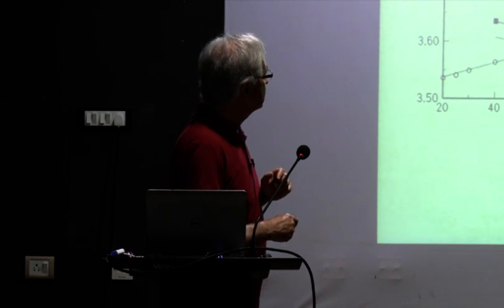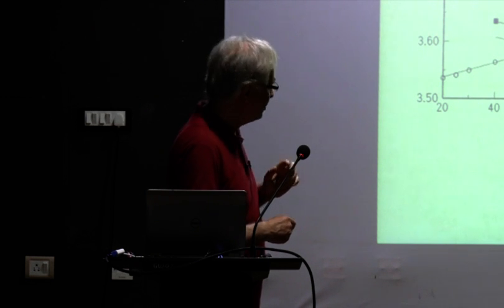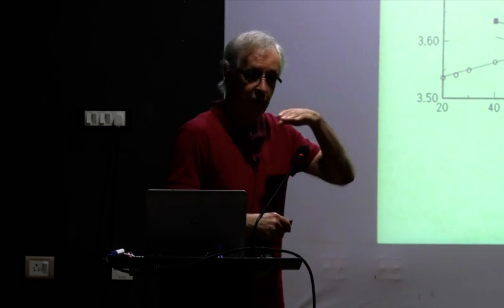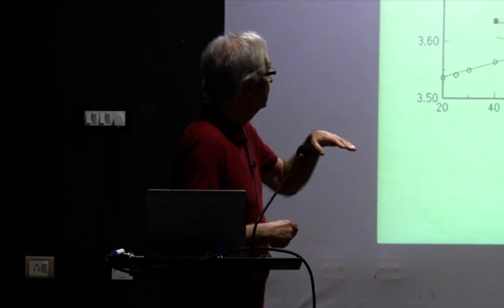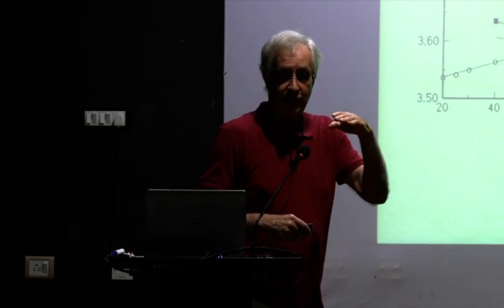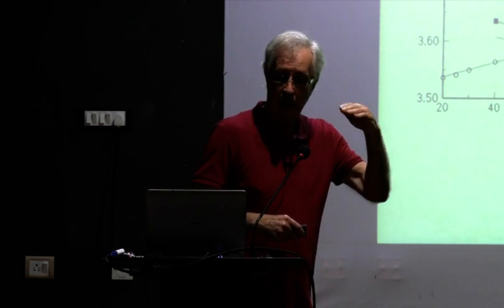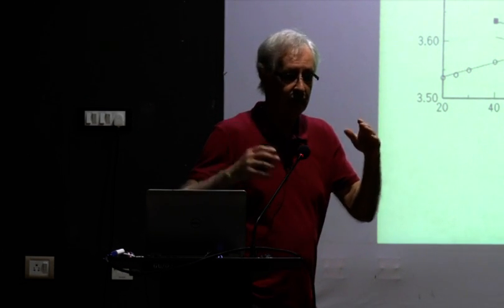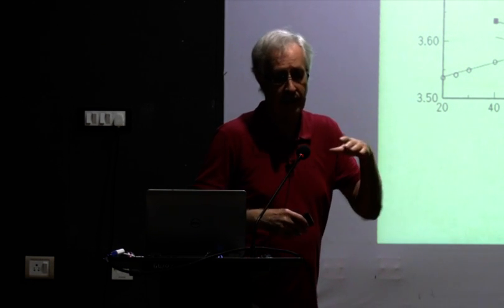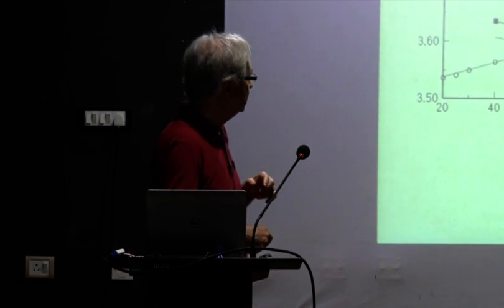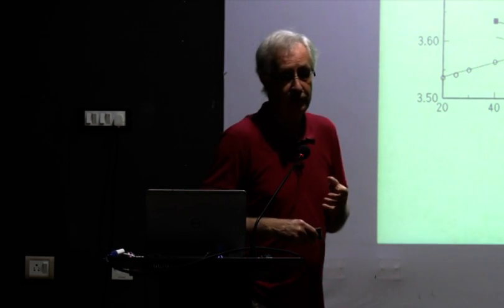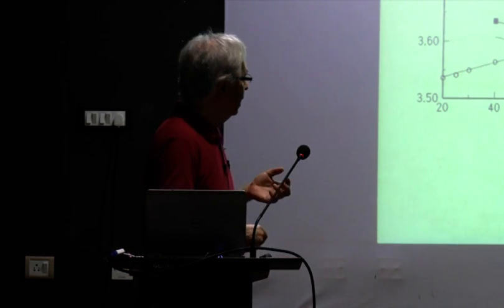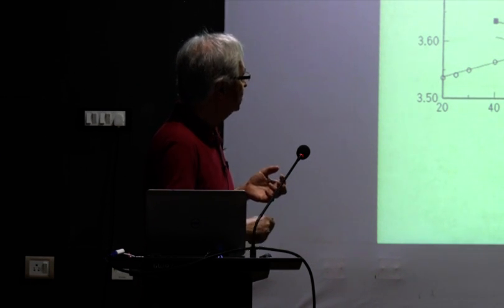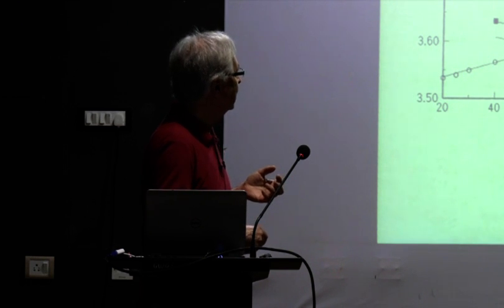You have here a substrate which is copper with a certain lattice parameter. You grow FCC iron on it. And then you can make another substrate. You can add a little bit of gold to copper so that you increase the lattice parameter, and you put iron on it again. And what happens is that the hyperfine field, which is proportional to the magnetic moment that you have, all of a sudden jumps from an antiferromagnetic case to a ferromagnetic one at a particular atomic volume.